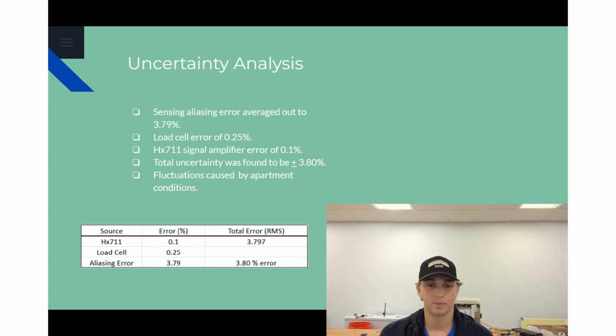We also see a 0.25% error from the load cell. This error is from the load cell assuming the relationship between voltage and force is linear, while in reality it is not. Some of this error also derives from manufacturing tolerances of the load cell. The last uncertainty we see is from the HX711 signal amplifier. This error comes from noise, as when the signal is amplified, error is introduced due to random fluctuations caused by scaling imperfections. On our graphs, we see some small fluctuations like random spikes or drops in the recorded data. These are caused by small bumps or vibrations, as when we did the experiment, it was in an apartment where you're bumping into tables and whatnot.